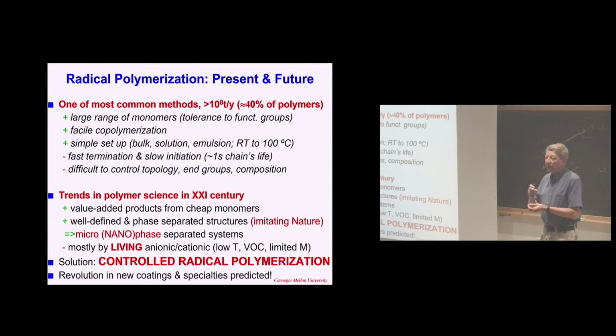Typically you dose radicals to a system continuously and slowly. If you take peroxide or take a diazo compound like AIBN, it has a half-life time of 10 hours, and every moment one radical is formed, it propagates, and after 1 second, it terminates. And the new radical is born, propagates like crazy with a monomer addition frequency of less than a millisecond, and then it's gone. So you cannot make block copolymers, you cannot make any functionalized structure. So it's impossible to control topology, end groups, or composition.